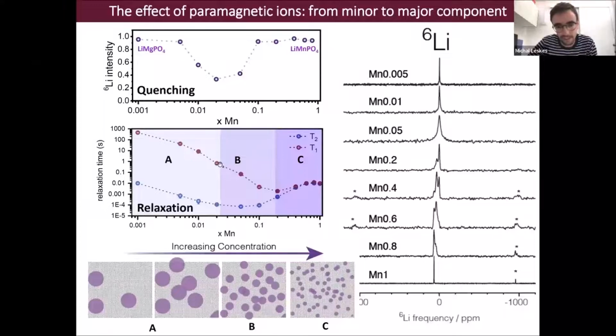And at this point, you can see that the ratio between T1 and T2 starts shrinking. So this means that the electron-electron interactions make the fluctuations of the magnetic moments of the electron faster and faster. And what happens because of this is that the relaxation time starts increasing at some point. So we revert the trend. You can see, for example, that here T2 is increasing, although we are increasing the amount of paramagnetic centers. And at some point, this also happens for T1, until we reach here the extreme narrowing regime. And at this point, we cannot say anything anymore about the correlation time.